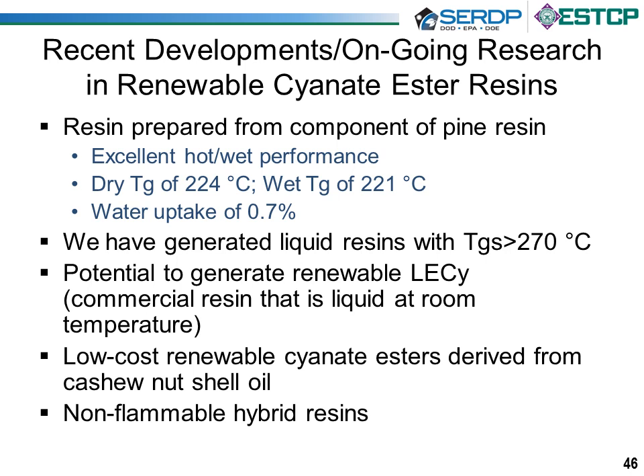We've developed a process to potentially generate renewable LECy, so that would be the same resin as the commercial resin I talked about a little bit earlier. And we've looked at really low-cost cyanate esters that can be derived from cashew nut shell oil. Cashew nut shell oil can actually be purchased for around $1 a pound, so we believe we could make very low-cost resins from that. And we've done some more work on non-flammable hybrid resins that incorporate phosphorus.